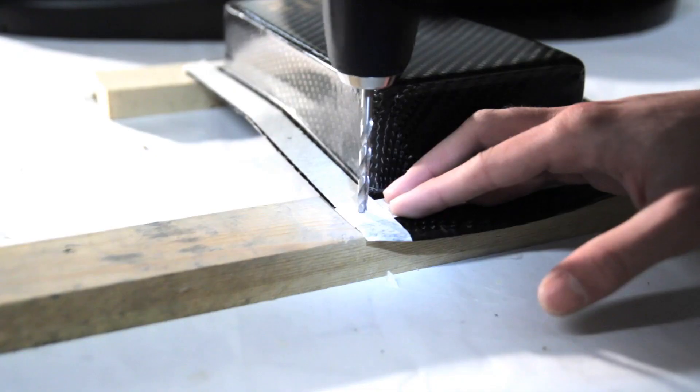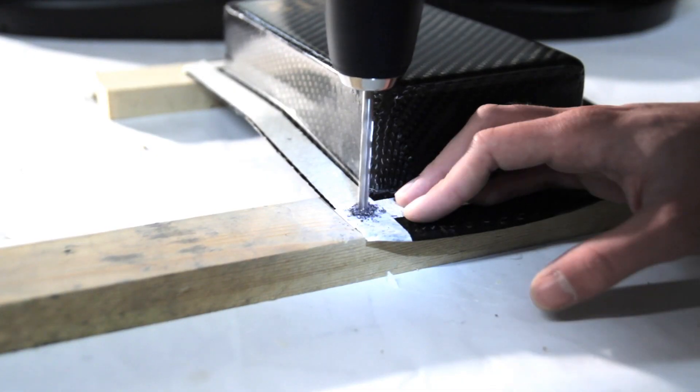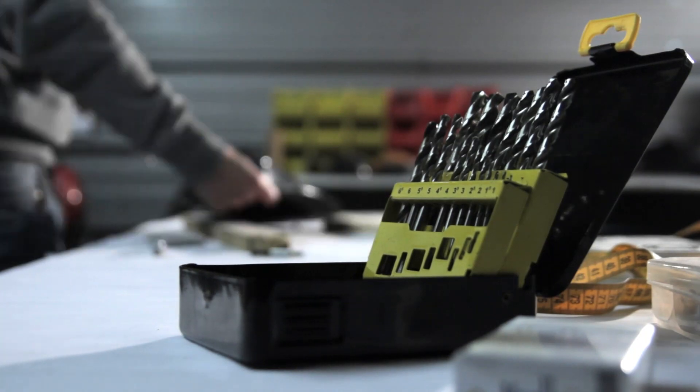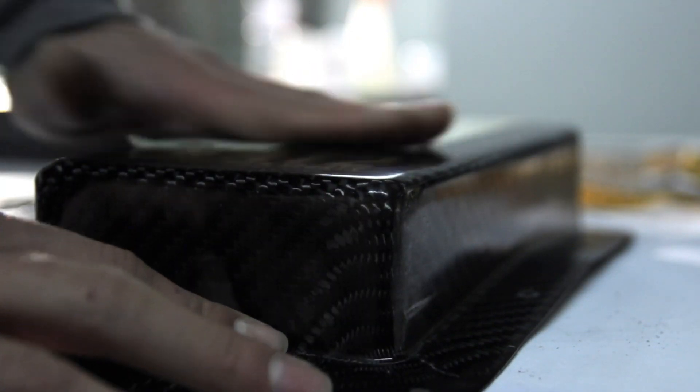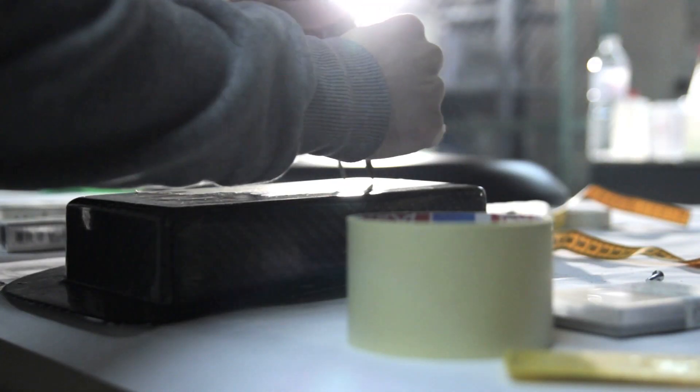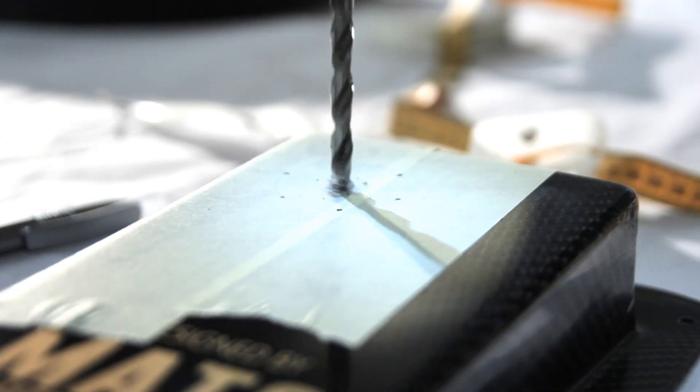Here I'm doing some measurements. You can drill through carbon fiber with just a normal drill, but they will dull out after a while, so don't use too expensive ones. Use tape on top of the part you want to cut just to avoid splinters and so on.